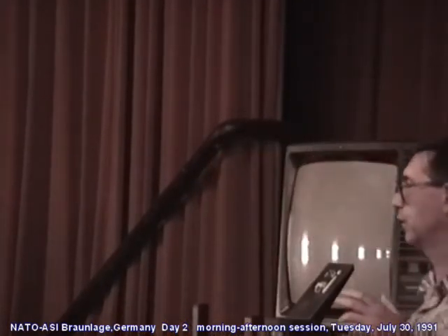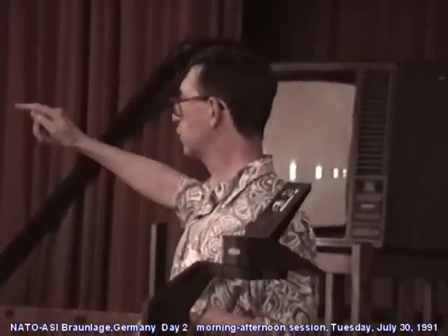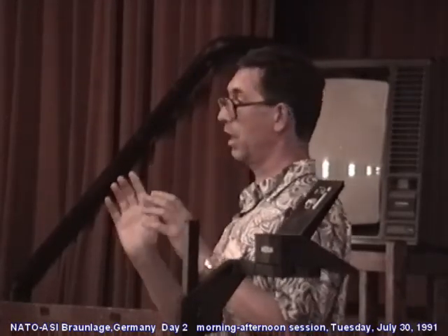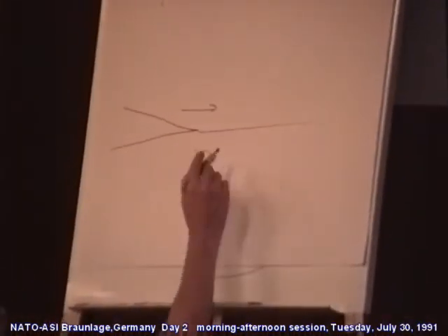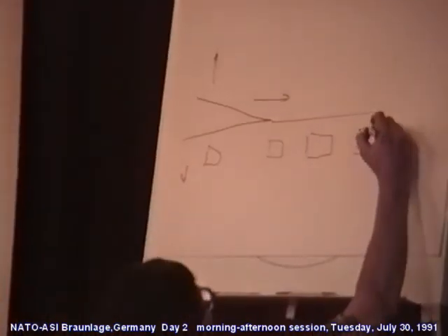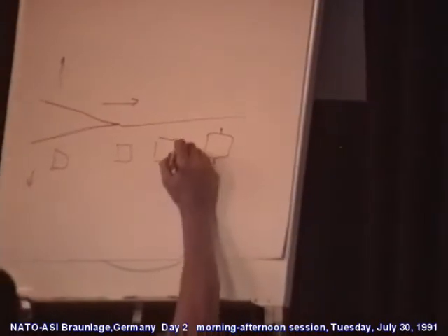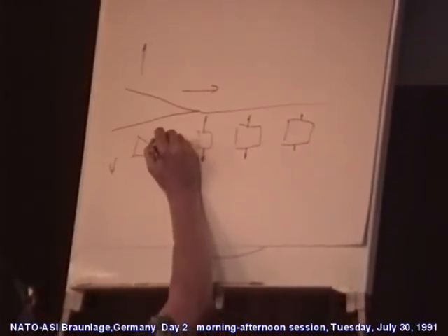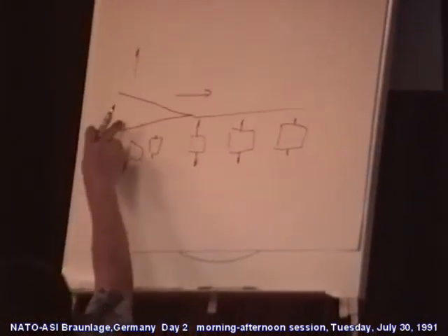And we can correlate the frequency with the velocity of the crack. Because if you assume you have a crack propagating in this direction, and if you look at some element of volume just below the crack, this element of volume sees more stress, and the stress increases as the crack approaches, and then decreases to zero. And you have a cycle of deformation whose duration is a function of the crack velocity,